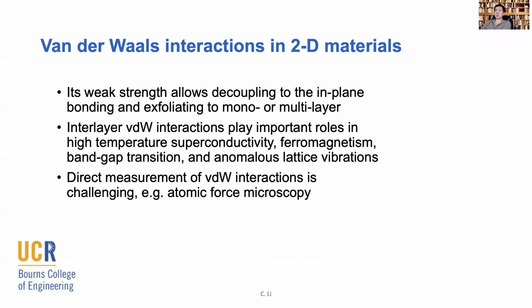Many of you are probably already familiar with this, but what we do know is that van der Waals interactions exist in many layered compounds, and that gives very weak coupling between layers, and sometimes allows exfoliating those layers into mono or multi-layers. We are actually going to come back to this later. It turns out this interaction is weaker than many people would think in terms of phonon dynamics, and we actually observe a lot of dynamics similar to what a monolayer would show. Also, the van der Waals interaction plays important roles in many physical phenomena.